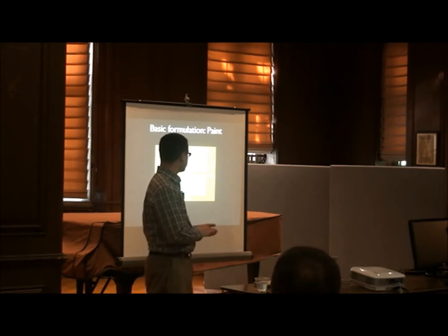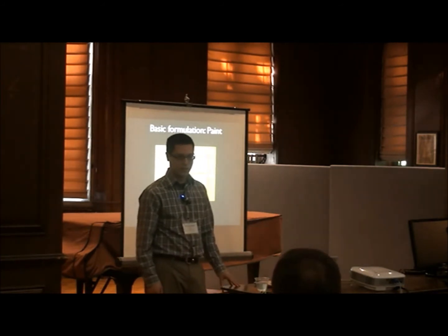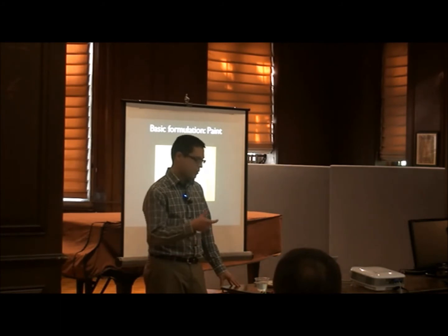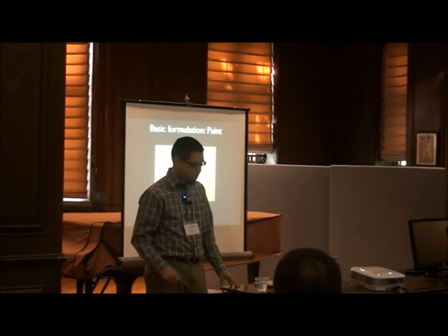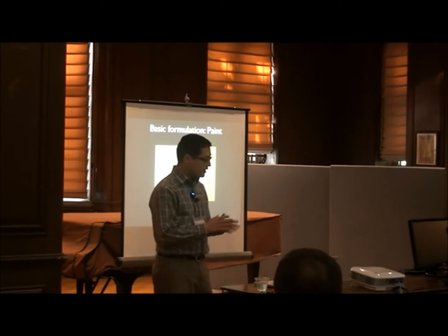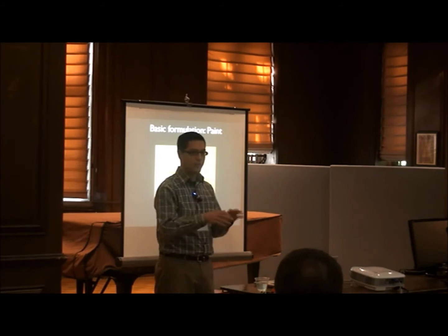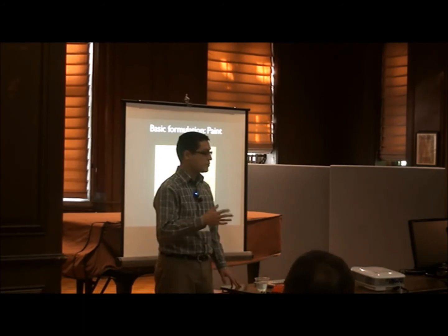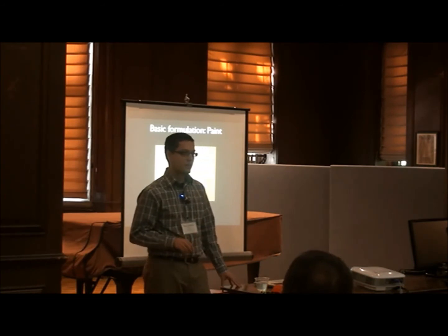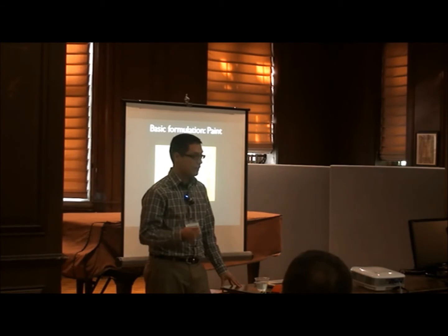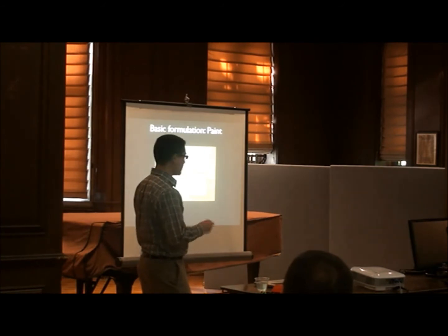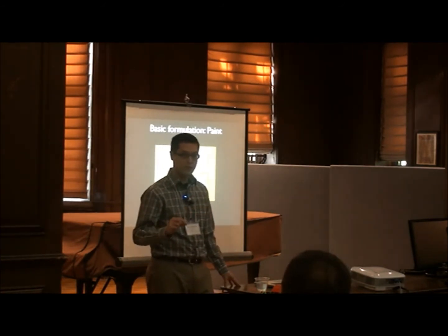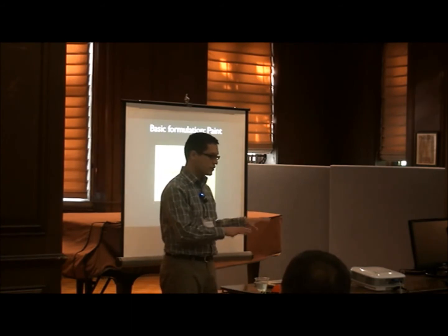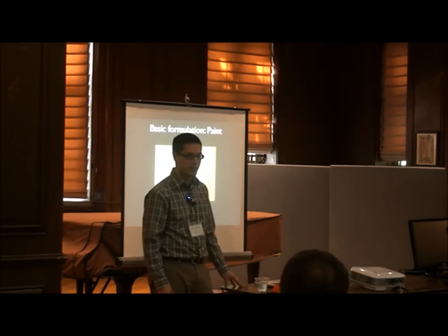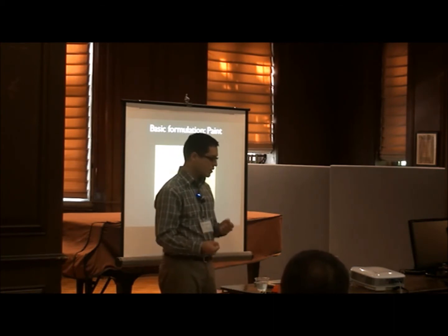At this point, the reflective coating is really the secret sauce that we've developed. And intuitively, if you just took this block of clear rubber and you spray painted it, well, that might create a nice looking surface, but then as soon as you touched it, that paint would probably crack and break and maybe even flake off. And the key properties that we need are an elastic, opaque, and thin coating. We don't want this reflective coating to be too thick, because then it will act like a blanket and it will cover the surface and you won't be able to see the very high resolution details. But you really need a stretchy, reflective, opaque coating.